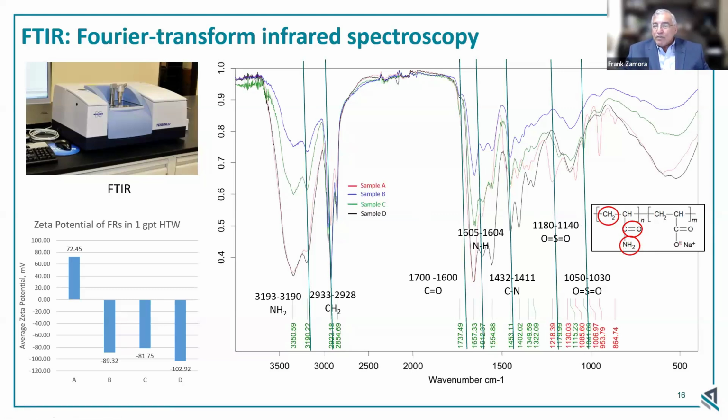So it's going to look at the carbonyl bond, for example. These carbonyls are this C double bond O. And then we look at the CNs, the NHs. So this spectrometer goes through its infrared signal, and it converts some of these signals into how it identifies the bond in the molecule itself. So these bonds are going to occur in certain parts of the wave number.